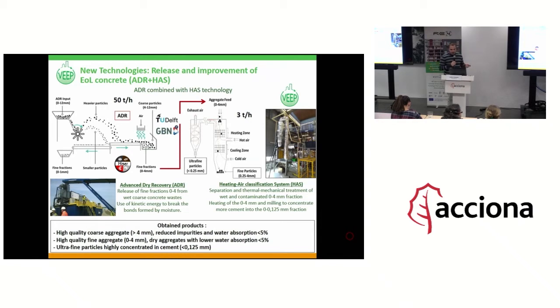So for the fine fraction, we developed another technology, a heating air technology. This technology applies air at high temperature, at 500 degrees, in order to remove all the moisture and the impurities of the material. It burns the impurities, and it also separates the ultrafine particles from the fine particles, the zero for the sand fraction to the ultrafine fraction.